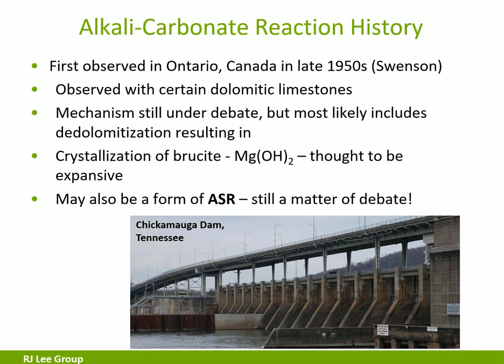So what happens with ACR is you begin to get dedolomitization of the dolomitic aggregate, and that causes expansive brucite formation. And we're finding a lot that sometimes that expansion is correlated with some ASR expansion from very fine microcrystalline silica within the aggregate as well. So that is still under debate.